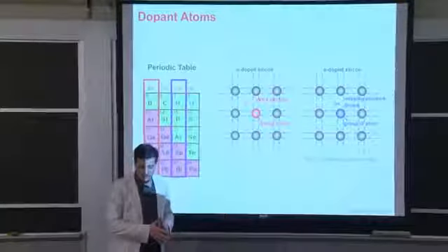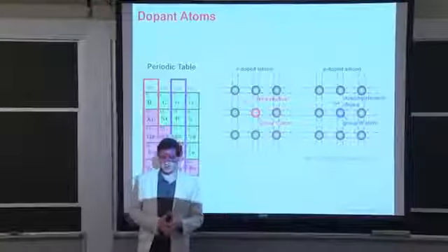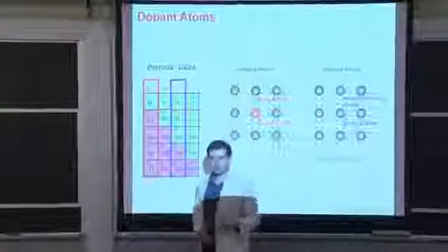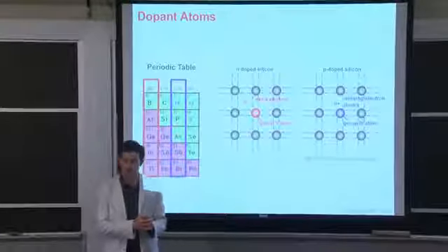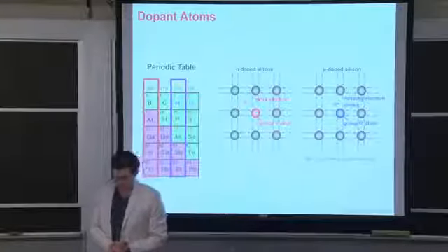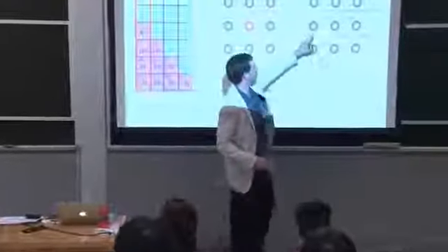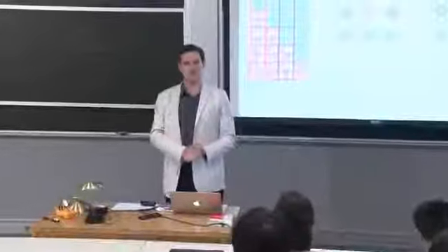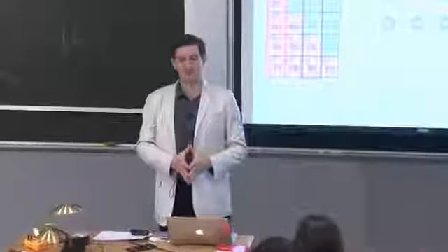Another way that we have very strong evidence that boron is occupying a substitutional site, not an interstitial site, is that we can calculate the binding energy of this hole to the boron atom on the substitutional site. In principle, if the interstitial was a charged defect, we could calculate the binding energy of the charge to that defect. Density functional theory could tell you which is more likely, given your experimental observation that you get about one hole for every one boron atom inside of your sample. Boron has been studied to death in silicon. It's pretty well known that it's substitutional. But if you're working with a new semiconducting material, you never know. You have to run the experiments.